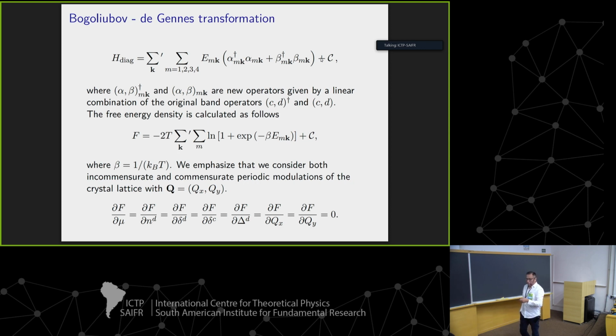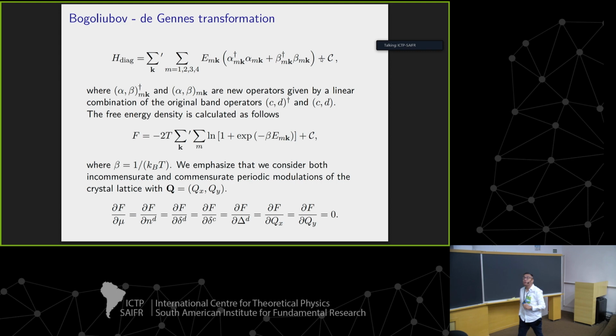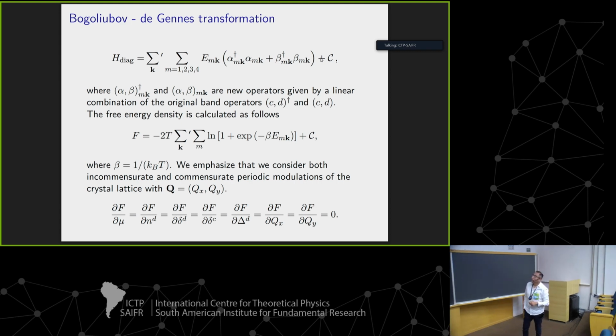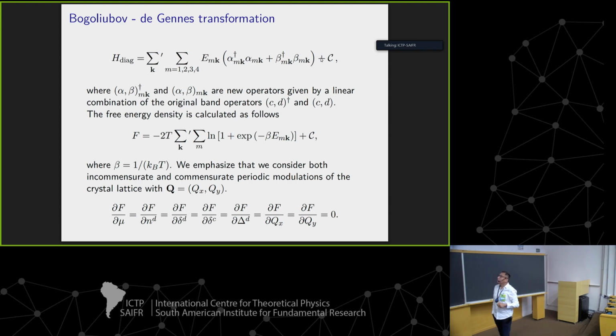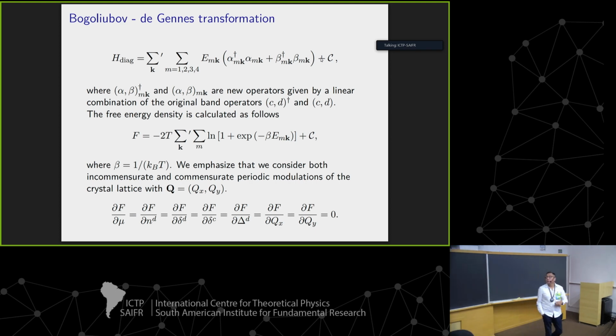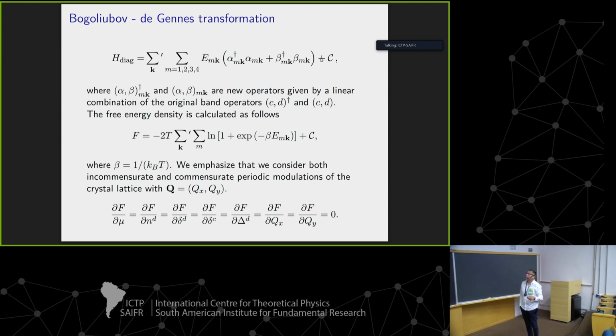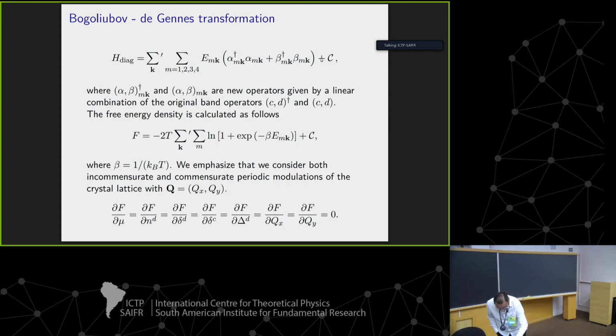How? Well, by using the Bogoliubov-de Gennes transformation, we have the diagonalized Hamiltonian, right, in this standard form, right? And this guy here is the eigenvalues of the matrix that I showed you before. Also, the free energy is put in this form, and we can get all the parameters that we introduced in our model by a minimization of the free energy density. So by solving all these equations here self-consistently, okay? All right.